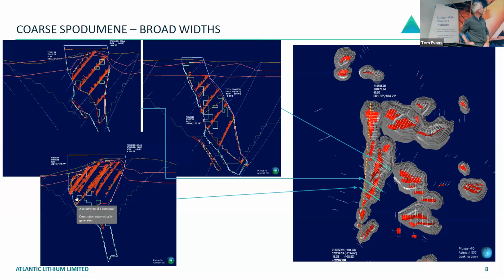And then in the Ewoyaa main section, in this lens here, that's roughly 500 meters long and at surface 100 meters wide. So it blows out into this wine glass shape. There are a few other pegmatites around the world that actually show this as well. So it must be something to do with those emplacement controls, structural controls, pressure, temperature scenarios around that emplacement. But quite interesting to see that same wine glass shape, which is also really useful from a mining point of view and strip ratios.